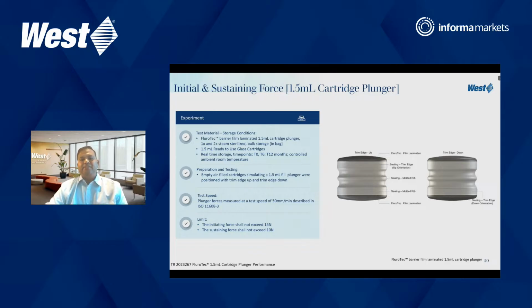So we had done an extensive study understanding the cartridge orientation, whether it is trim edge up or trim edge down. This study focuses mainly on the initiating force, which is nothing but the break loose force, and the sustaining force, which is nothing but the gliding force. We have done this study as per ISO 11608-3. We took these 1.5 ml laminated plungers and did 1x and 2x, meaning 30 minutes of steam sterilization and 60 minutes of steam sterilization, and performed the studies at time 0, 6 months and 12 months at controlled room temperature, just to understand whether there is any impact of trim edge as well as 1x and 2x steam sterilization on break loose and extrusion force.